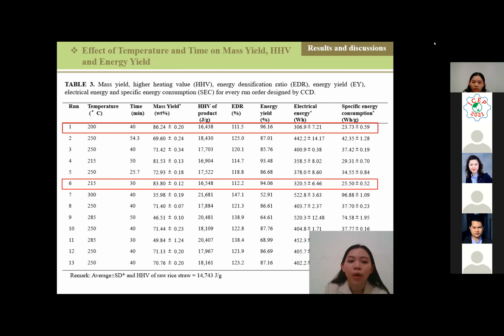In optimization, not only energy yield but also the specific energy consumption was considered. This was because the specific energy consumption indicated the energy used during the process per unit of torrefied product, which was practical from an economic point of view. It can be said that the optimized condition was obtained at high energy yield and low specific energy consumption. This led to the conclusion that there were two effective optimized conditions which gave high energy yield and low specific energy consumption. Firstly, 200 degrees Celsius 40 minutes, and secondly 215 degrees Celsius 30 minutes.